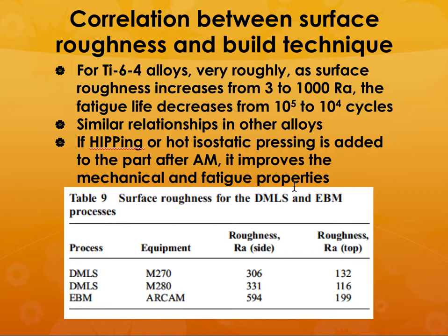So what are some of the effects of surface roughness as a result of the additive manufacturing technique on the properties? In this case, what they found was that the higher the surface roughness, the lower the fatigue life of these materials. So if hipping or hot isostatic pressing is added to the part after additive manufacturing, it improves the mechanical and fatigue properties, because those subsurface flaws are going to be eliminated as a result of hipping.